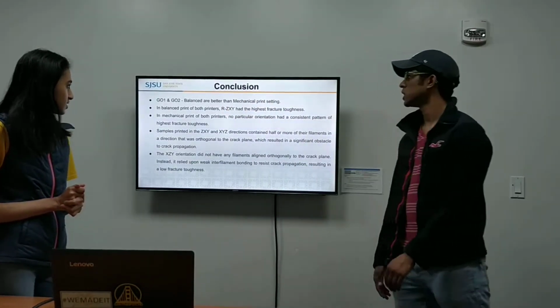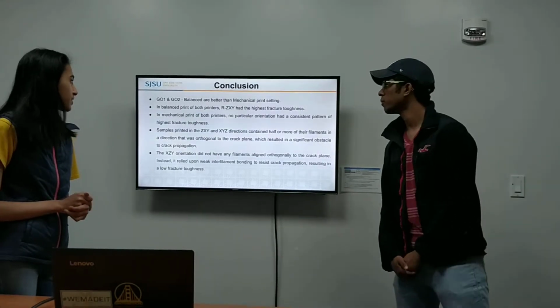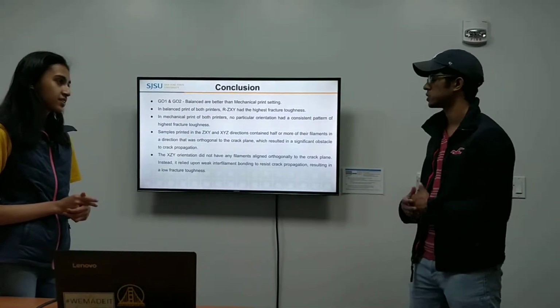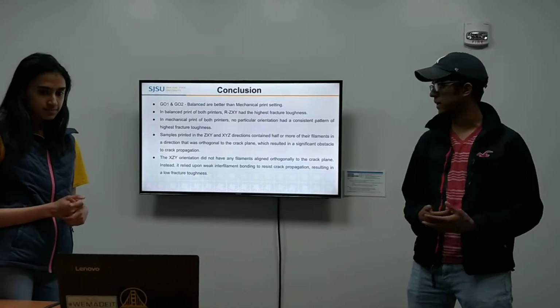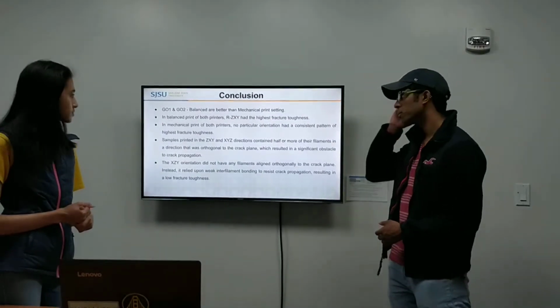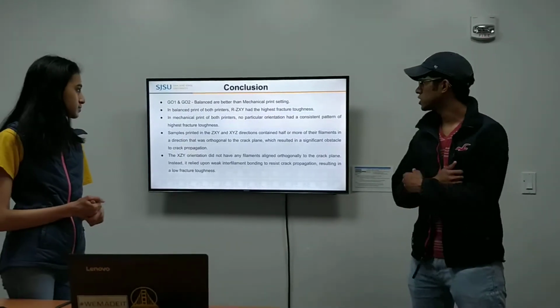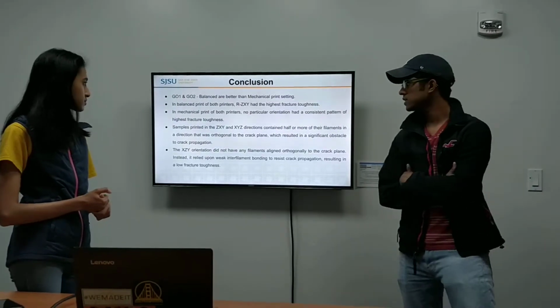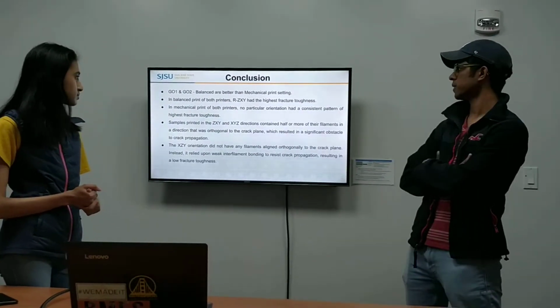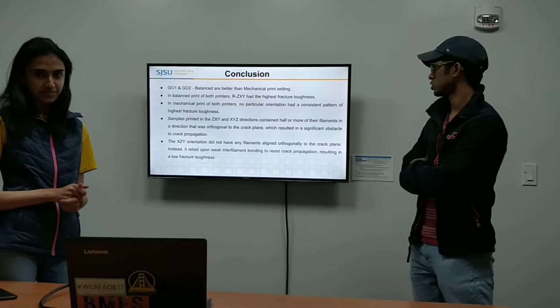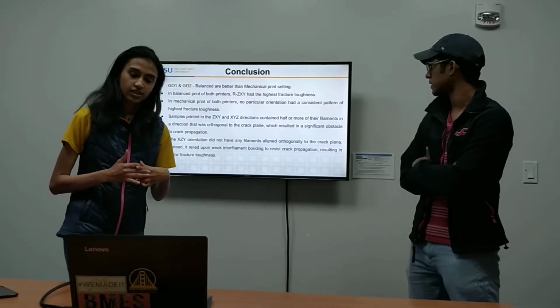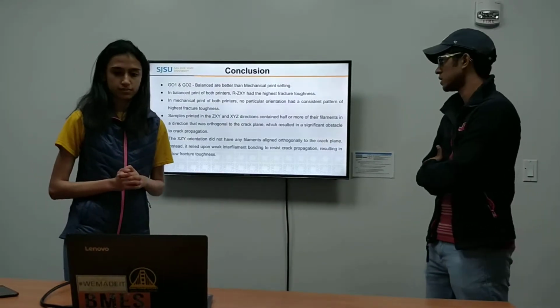So in conclusion, in both printer 1 and printer 2, balanced was better than mechanical, as expected. And in both printers, the ZXY orientation had the highest fracture toughness. In the mechanical printer, there was no particular orientation that had a consistent pattern of higher fracture toughness.